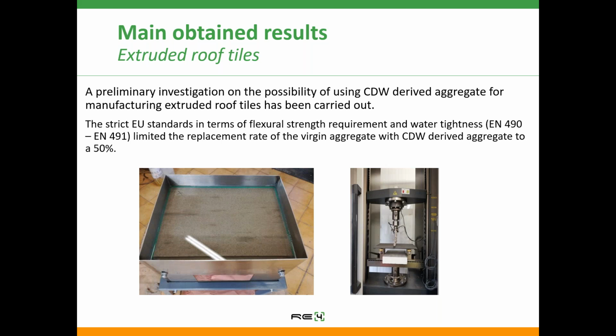And on the left, we have a 3-point bending machine to test the flexural strengths of the extruded roof tile. Basically, that percentage of replacement, which was set at 50%, was due to the fact that for the extrusion process, when we have to reach very high standards in terms of flexural strength and water tightness, we have to deal with a very well distributed Fuller curve, which is a representation of the grading of the ideal distribution of the aggregate size in order to get the most suitable density and the highest flexural strengths.